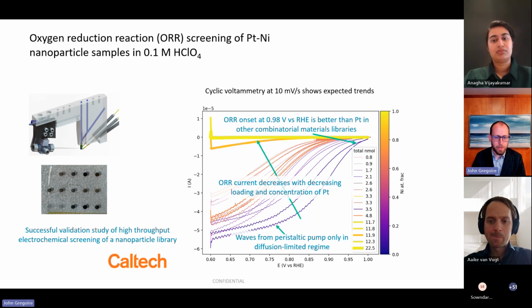And we're seeing a few features that look very promising to us in the ability for this synthesis tool to enable us to explore these kinds of composition spaces. One is that we have a very early onset. This is much better than anything we've gotten from our other high throughput synthesis techniques, likely due to the very high surface area of these nanoparticle systems. And it could also be the preferential exposure of edge sites and other things.